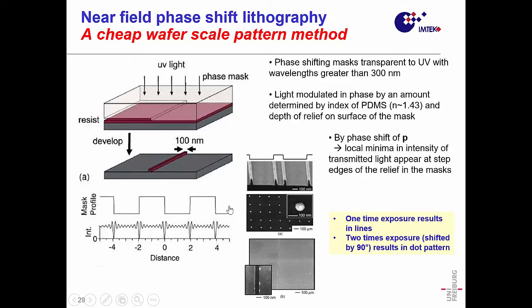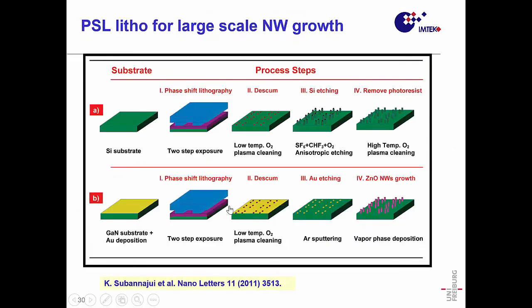It's a very simple process. If you have a clean room and then UV exposure there, simply prepare a mask profile as you see here with a step, then make a flooding exposure, and at the edge of the steps you're getting an overexposure. You can use that on your resist. One-time exposure gives you lines, two-time exposure gives you dots, and that you can use then for the growth of nanowires or nanowalls.